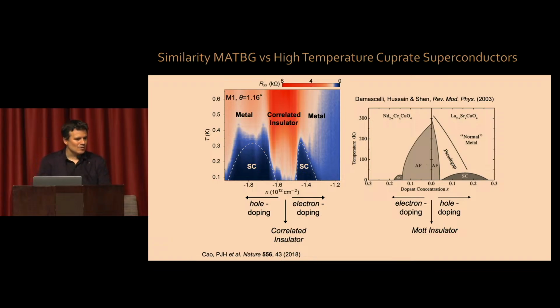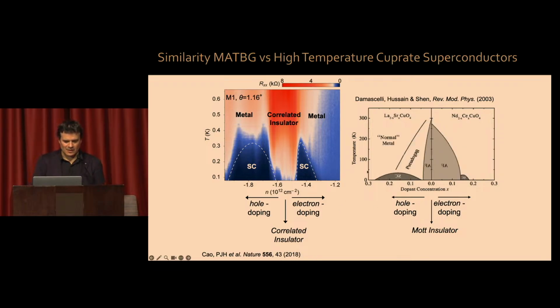So when my students showed me this data, I was immediately shocked, because this reminded me of the hundreds of times that I had seen these diagrams. Let me flip it, because now electrons and holes are in the right direction. Okay? In high-temperature cuprate superconductors, when you put 1 electron per copper atom, you get a correlated Mott insulator. And if you add a few extra electrons or a few extra holes, you get superconductivity. In magic angle twisted bilayer graphene, when you put 2 electrons or 2 holes per moiré unit cell, you get a correlated insulator, and you add some holes or electrons, and you get a superconductor.